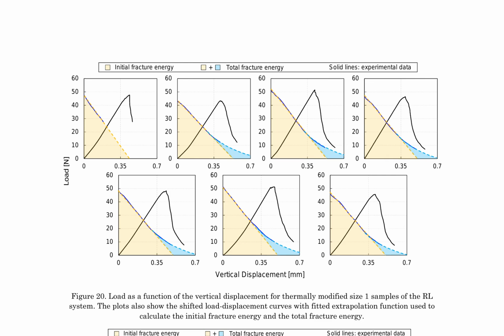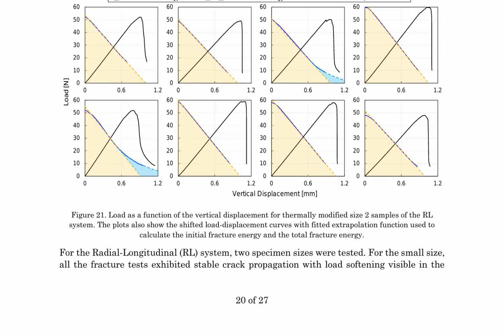The load displacement curves for small size samples, shown in figure 20, feature solid lines representing experimental data, illustrating the relationship between load and vertical displacement. Fitted extrapolation functions enable the calculation of initial fracture energy and total fracture energy. Similarly, large size samples' load displacement curves, presented in figure 21, include shifted curves and fitted extrapolation functions for determining fracture energies.